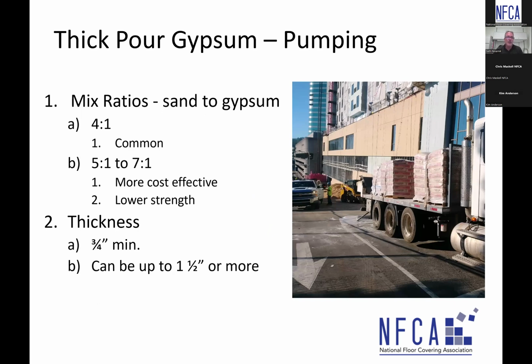So mix ratios: very common is a 4-to-1 ratio, sand to gypsum. Sometimes it's a 5, 6, 7-to-1. But by adding more sand, it's certainly more cost effective, but we take away from the strength development, because the sand would be the foreign material in there. The gypsum is the binder that holds everything together. So by putting more sand in there, we have less binder. The risk is we lower the strength. We'll talk about compressive strengths and strength properties in a slide coming up as well.